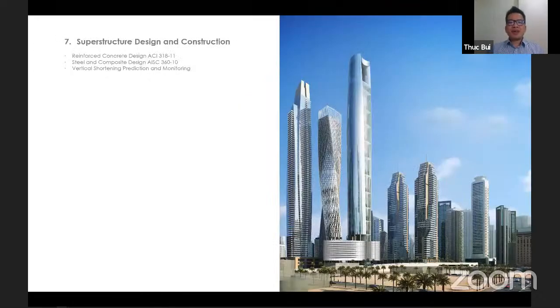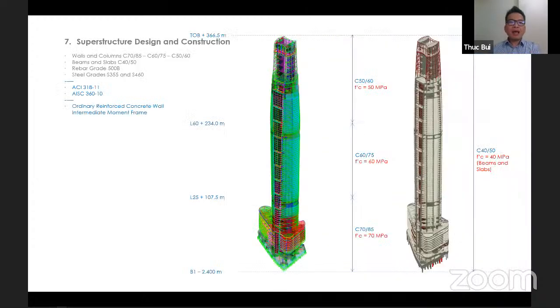Going to the superstructure design and construction, in this project, reinforced concrete design is done according to ACI 318-11, and steel and composite design is done to AISC 360-10. For the vertical elements, concrete cylinder strength is 70 MPa for the first 100 meters of the towers, and then for the neck part of the tower, the next 120 meters, the concrete cylinder strength is 60 MPa, and 50 MPa for the remaining structure. The rebars are of grade 500B, so the yield strength is 500 MPa. For ductility and detailing, we comply with the ACI provisions for ordinary reinforced concrete work and intermediate moment frames.